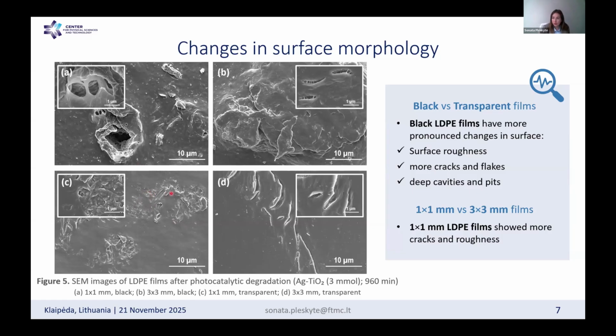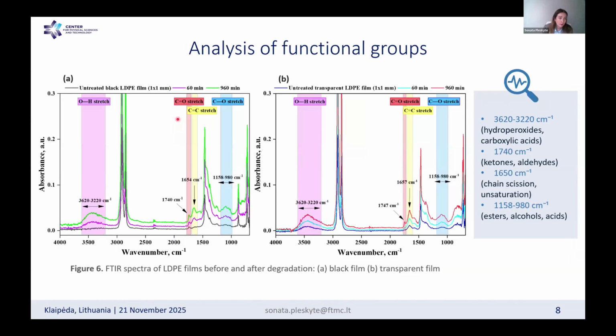And here I would like to remind you that a few slides before, I showed you the SEM imaging of the pristine LDPE films, and you already noticed that the black LDPE films had some defects like flakes and wrinkles on the top surface layer. We believe that especially these defected regions on the top layers of black LDPE films can be the initiation sites for the oxidation processes, and therefore more changes are obtained after the photocatalytic degradation reactions exactly on the black colored LDPE films. And the following figure represents the FTIR analysis of both color films over the degradation time of 16 hours.